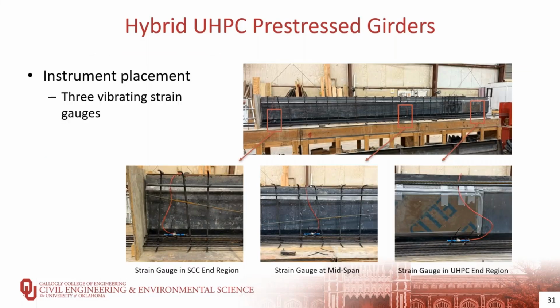After we did that, 3 vibrating wire strain gauges were used and placed at 3 locations. 1 foot from the live end, and here I'm going to start referring to the live end as the end near where the tension was applied. And then the second vibrating wire strain gauge was placed at midspan, and the last one was at 1 foot from the dead end, which is the other end. They were all placed on the top 2 strands and attached to them using zip ties.